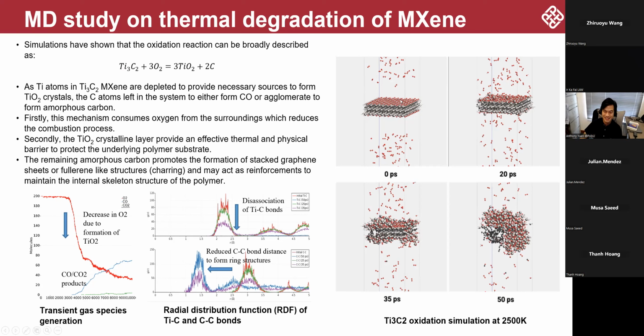Just getting this nanosheet stabilized in the MD takes a lot of effort in optimizing the so-called reactive force field. Precisely, the bonding force between the molecules has to be optimized, and it can be done with the embedded functions in MD using some AI techniques revolving around density functional theory.